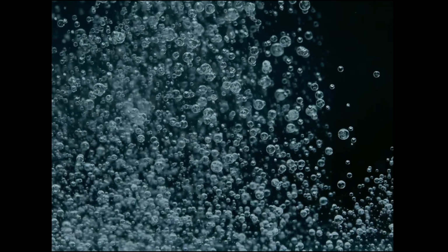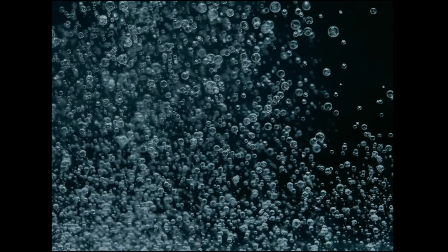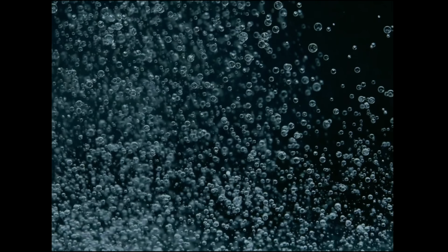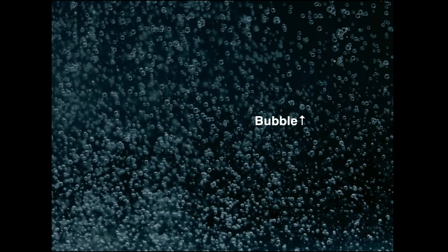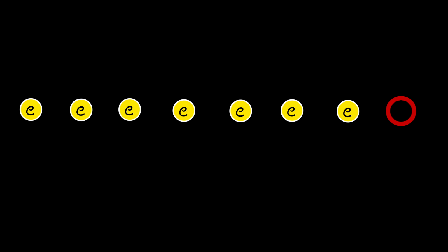It's kind of like watching bubbles move through a column of flowing water. The bubble itself is just a location where water is missing, just as the hole is a location where an electron is missing. While water flows downward, the bubble moves upwards. It's much easier to track one bubble than it is to try to follow the movement of all of the water. Similarly, the movement of a hole is really just the movement of a bunch of other electrons, but, like the bubble, it's a lot more convenient to just treat the hole as if it were a real, single particle with a positive charge, itself contributing to conductivity, just like the mobile electron.